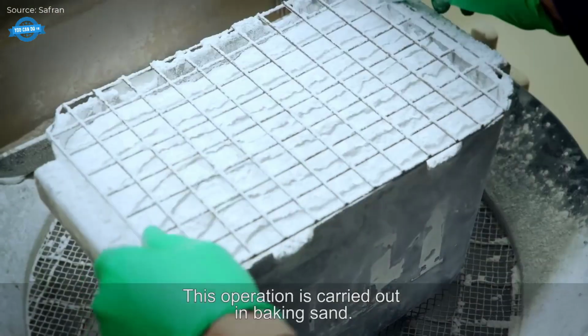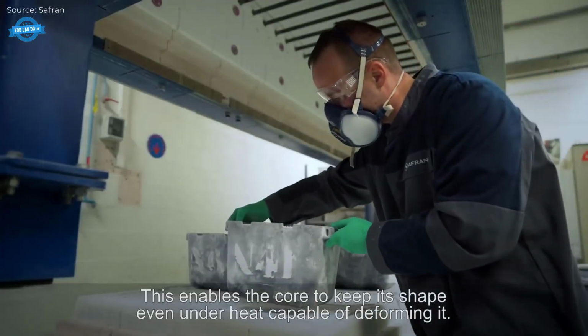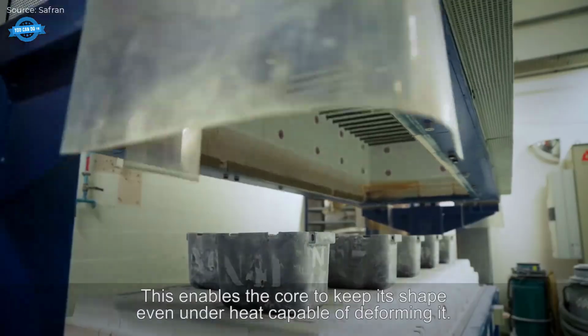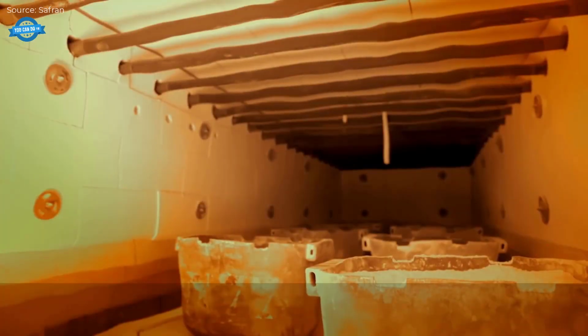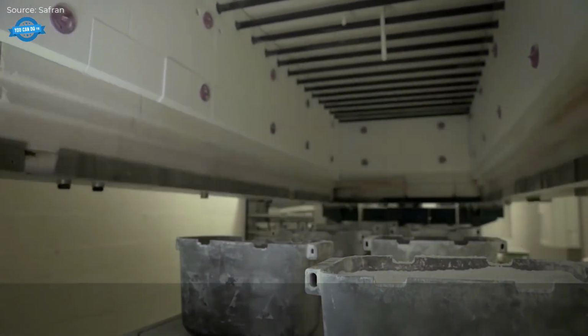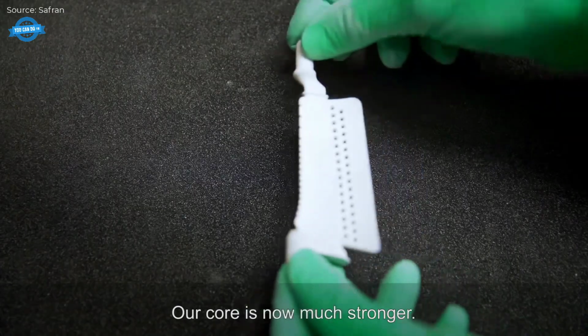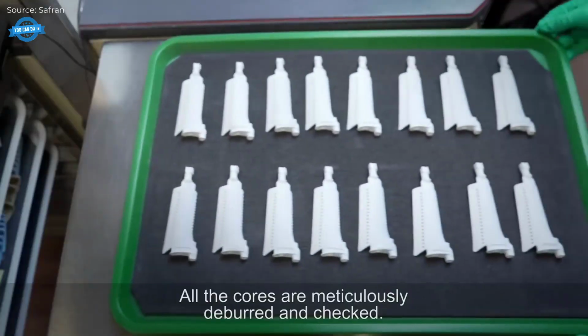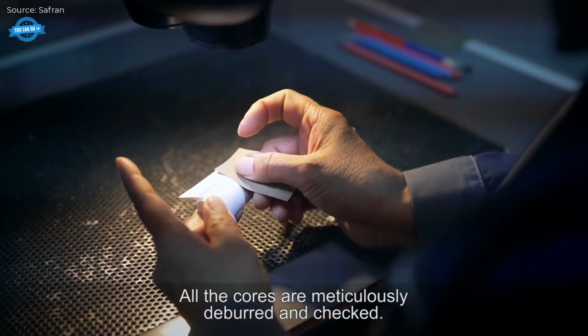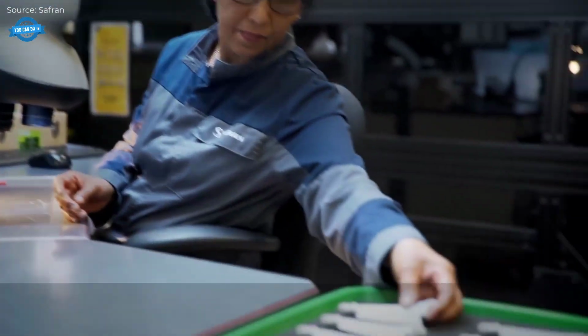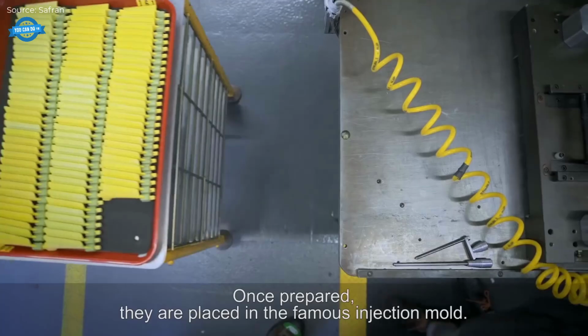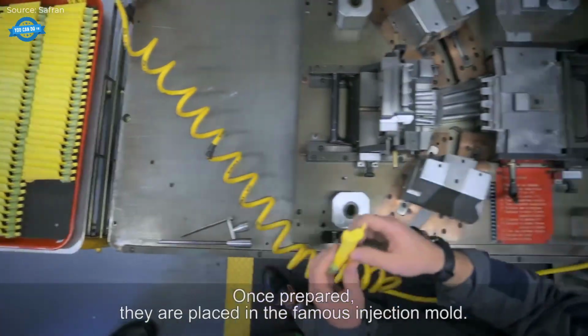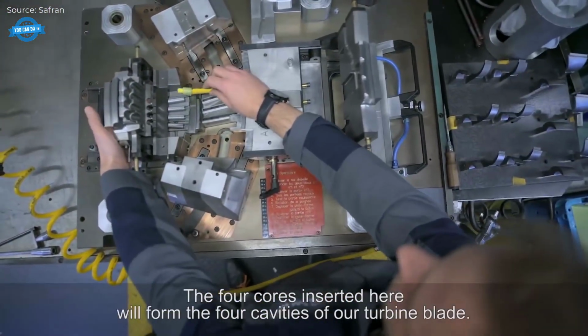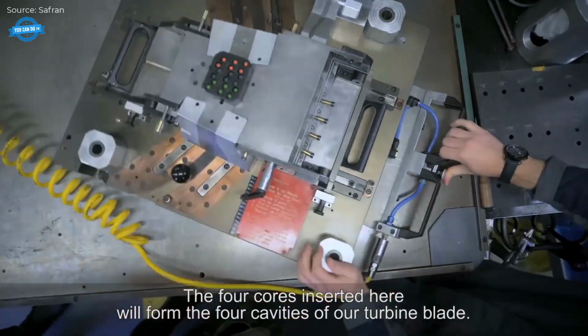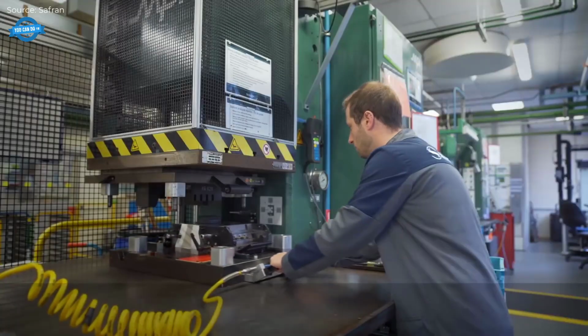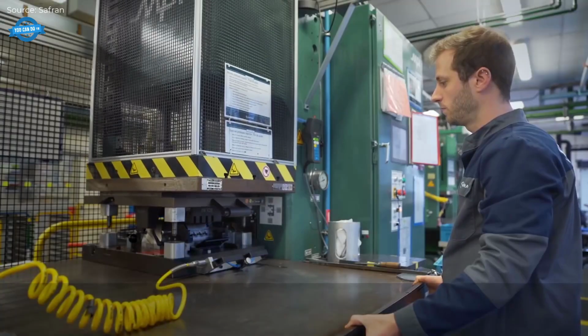The production of turbine blades involves lost wax casting, an ancient technique modified with modern advancements to achieve precise, complex shapes. First, engineers produce a core, essentially a mold within a mold, which defines the internal cooling channels of the blade. A mixture of binder and ceramic material is injected into a core machine to produce this core. The cores are fragile initially, so they are baked in a special sand mixture to harden, allowing them to withstand high temperatures during subsequent stages.